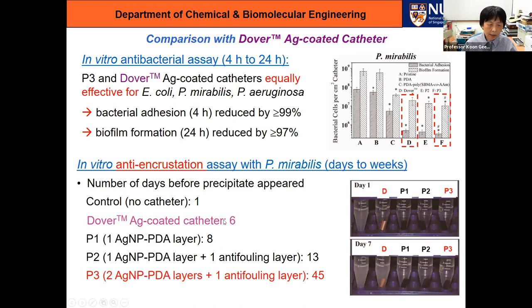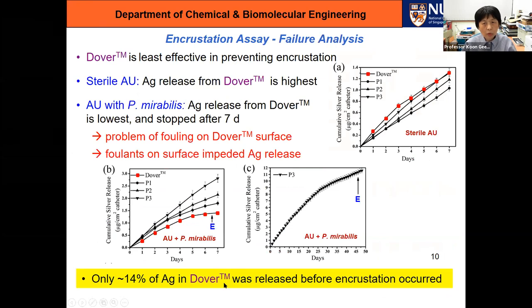And the Dover catheter lasted 6 days. So on day 7, you can see the D for the Dover has already resulted in precipitate. Our P1, this is our coating, with just one silver layer, lasted almost the same time, because it's almost the same as Dover, lasted 8 days. But if we just put the same single layer of silver with one anti-fouling layer, it prolongs its life by 5 more days. And we have 2 silver layers plus 1 anti-fouling layer, it lasted 45 days, which is much better than the Dover.